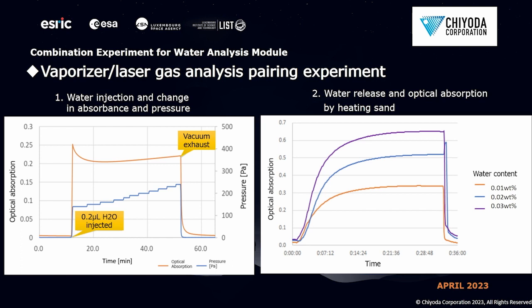And this is the result from TDLS. As you can see on the left-hand side of the slide, TDLS reacts right after the water is injected into the vaporizer. And from this experiment, we confirmed that this TDLS can measure very small amounts of water, such as 0.01 weight percent to 0.03 weight percent.